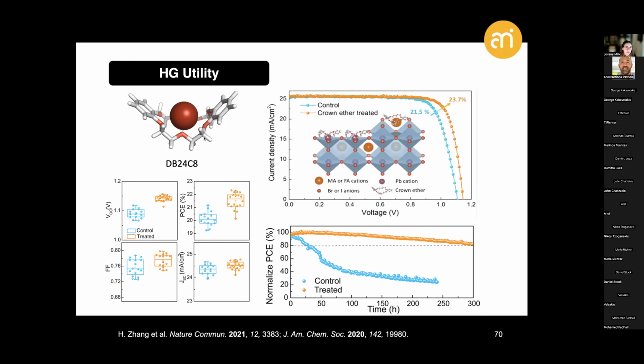the systematic screening of both aliphatic and aromatic analogs, with the purpose of interacting with specific ions at the interface of hybrid perovskites, especially those of under-coordinated lead cations and A cations. When the system is used as a molecular modulator from an orthogonal solvent at the interface with hole transporting materials, it led to remarkable improvements in performance associated with the suppression of some of the defects, but also operational stabilities related directly to this ion binding capacity,